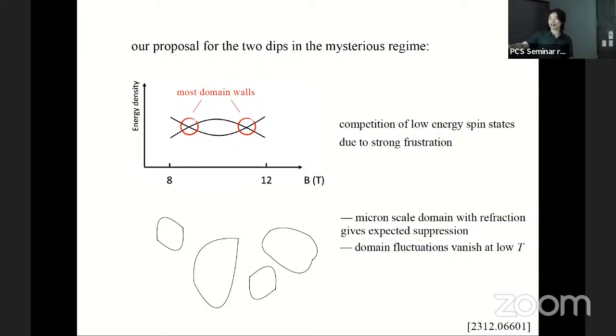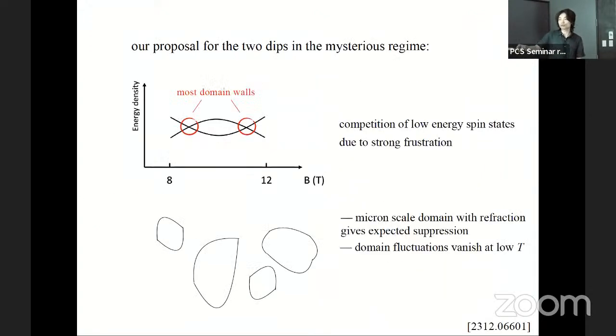And if we just analyze the domains, we assume the domains are of micron scales, and then the phonons will have refraction, maybe other scatterings across the domain walls. And this will be sufficient to give the expected suppression. And as we can see from the data, the suppression is by a factor of about one half or lower. Okay. So with reasonable assumptions about the domains, this can give the reasonable suppression.